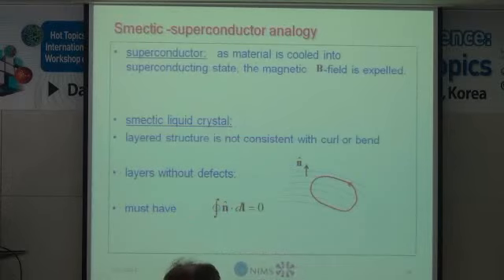Moving on. There's also a beautiful analogy that de Gennes pointed out between superconductors and smectics. So, as we all know, when you cool a superconductor into the superconducting state, the magnetic field is expelled. That's the Meissner effect. And if you have a smectic liquid crystal, which is a uniformly layered structure, it turns out that if there are no defects, this line integral around any closed path of n must vanish, because you're just counting the layers as you go around.